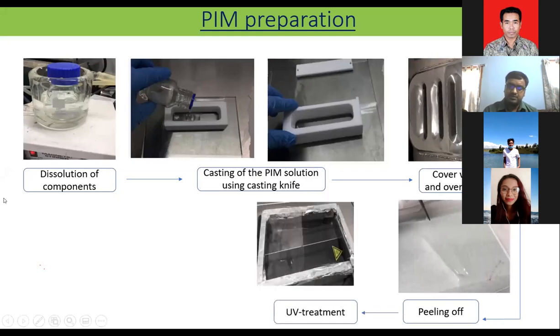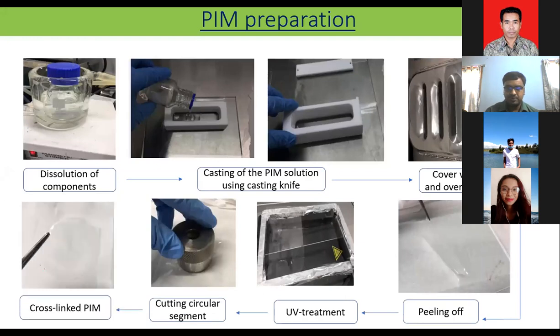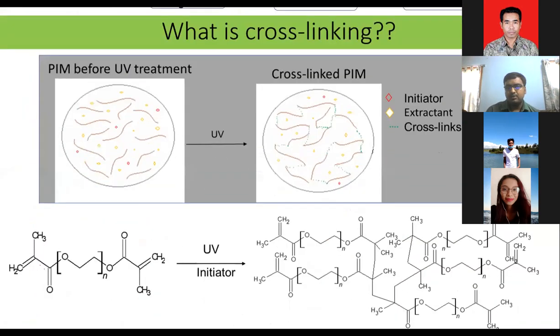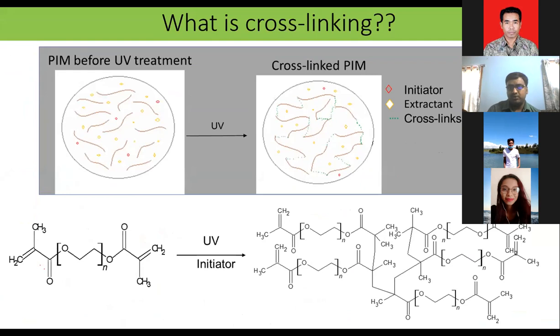This step is only for the cross-linking membranes. If you only cast a normal membrane, you can end it here. But for inducing the cross-linking, we need to do a UV treatment of the membrane. After the UV treatment, we get a cross-linked membrane like this, a transparent, homogeneous membrane. Before the UV treatment, the membrane is like this. You can see these are the cross-linking polymers or oligomers.